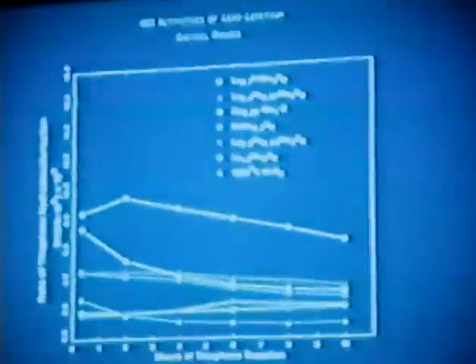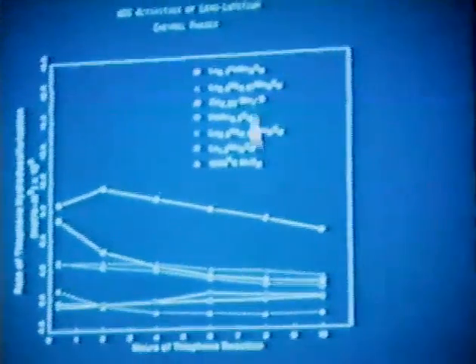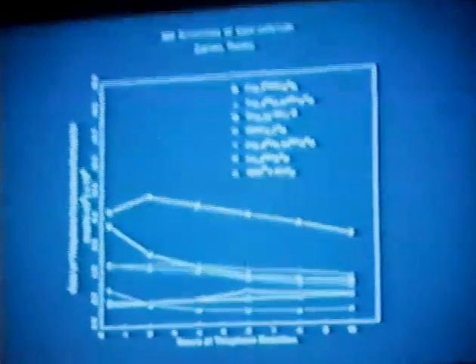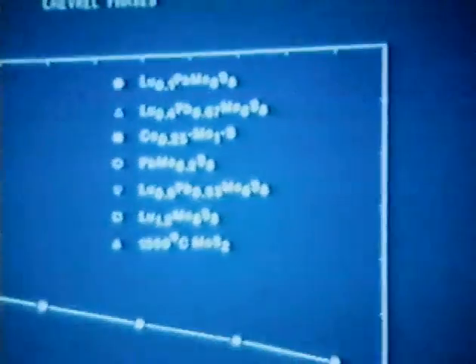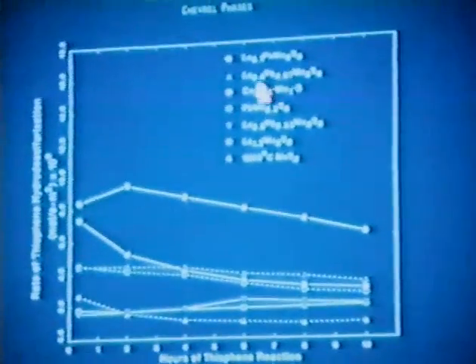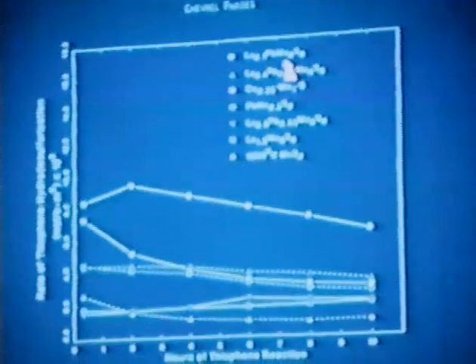In fact, we embarked on studying a series of Chevrel phase compounds in which you can form solid solutions of Chevrel phases involving the lead and lutetium Chevrel phase compound. And really what's happening here is that you are able to displace some of the lead large cation ternary metals with the lutetium. But there's a difference in the oxidation state on the lead and the lutetium. And what one can do here then is systematically vary the molybdenum oxidation state for the Chevrel phase compounds.